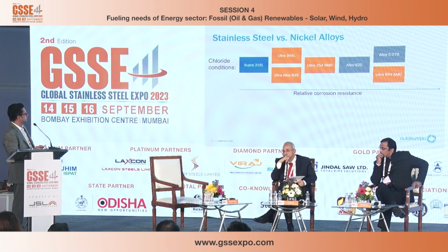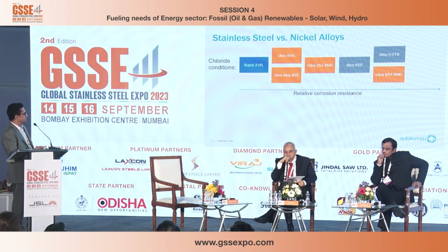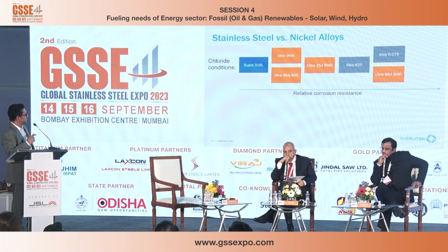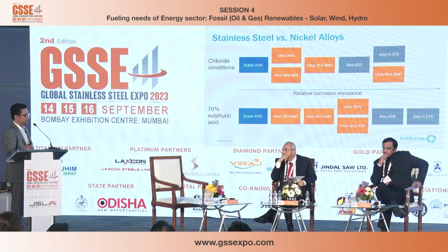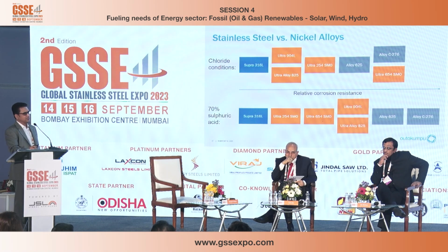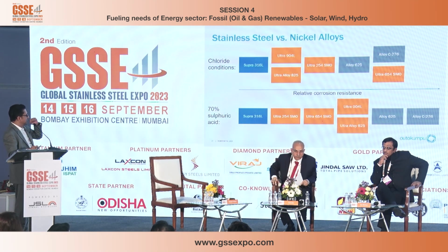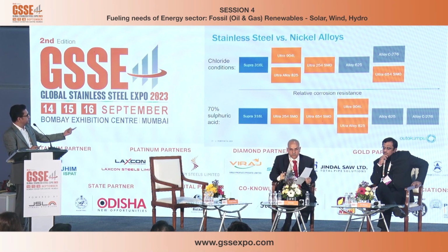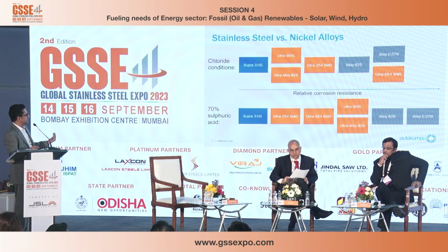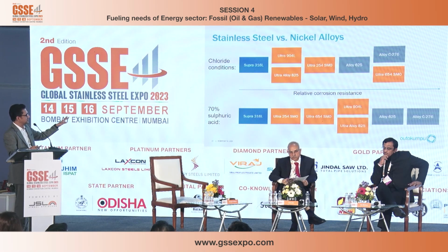If you are talking about the chloride conditions, this is the relative corrosion resistance. You start with 316L, then 904L, 825, 254 SMO, and then go to 625 or C276 or ultra alloys. But if you are talking about 70% sulfuric acid, you see the picture change. After 316L, the 254 SMO has shifted to the left, whereas 625 and C276 have gone up. So this is something you need to discuss with the material engineers, which grade and which application you need to select.